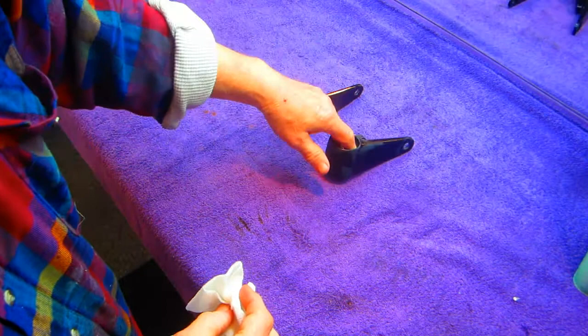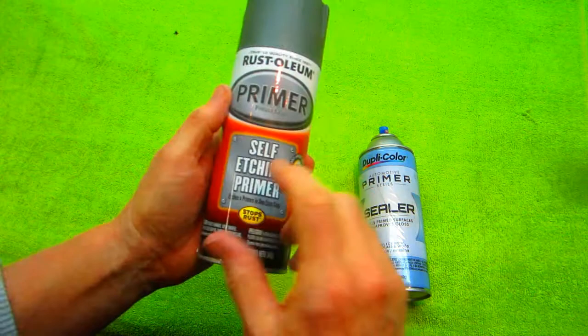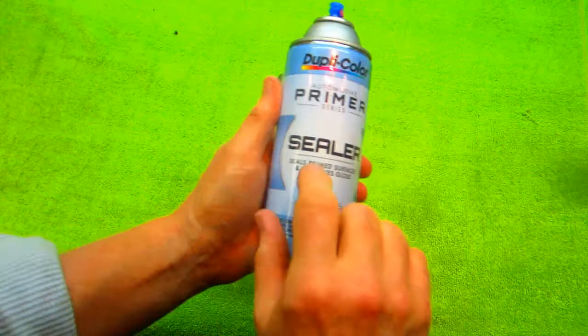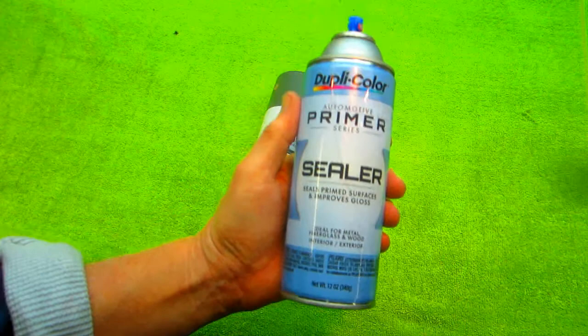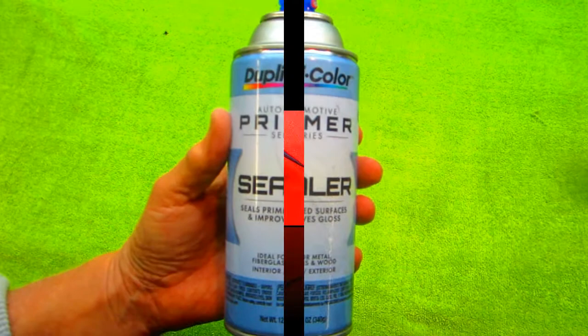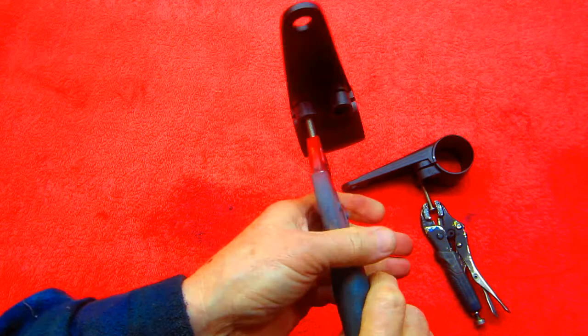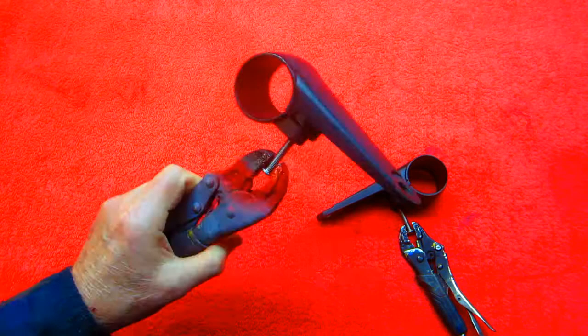Real good information here: if we were down to raw metal — raw aluminum — I'd want self-etching primer. When going over painted surfaces, I want a sealer-primer. It was actually Turbo Steve who brought the first can over for us to test, and it worked out really well. This goes on very watery thin, gets a good bite, and its only purpose is to bond the paint underneath to the paint we're going to put on. Luckily I have long bolts and vice grips to hold the parts for spraying — though the wind is still howling out there.